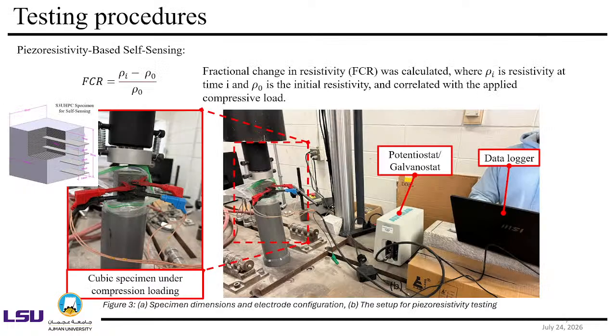Okay, so we want to test if it's self-sensing. What we do is we have a cube here, and we use a very typical self-sensing geometry, which is four probes. You give the outer two probes some electrical potential, and you measure the electrical potential from the inner two probes. That's what we often do.